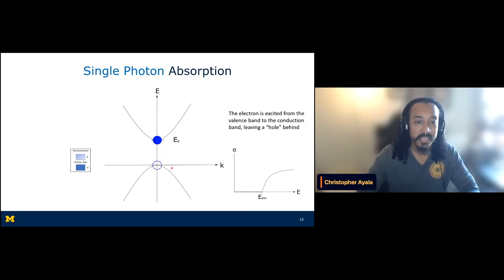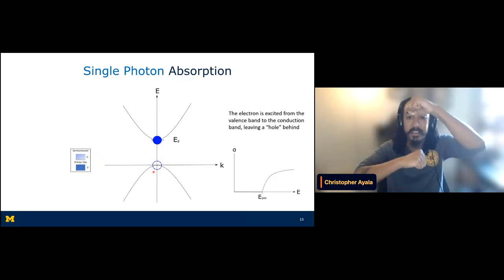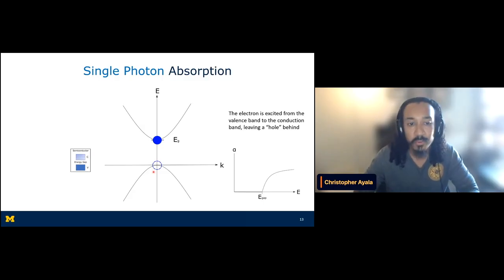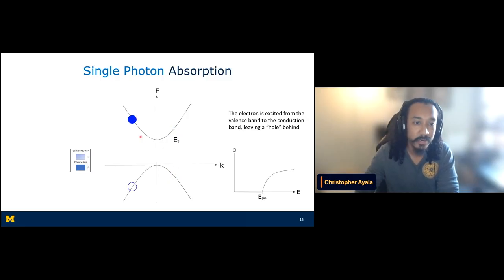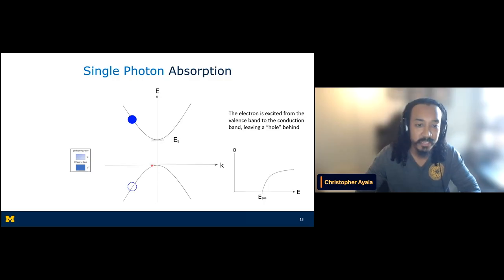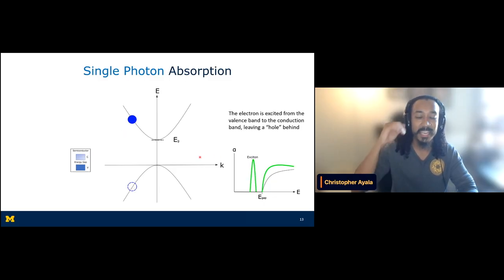And when an electron is excited from the valence into the conduction band, it leaves behind a hole. Note that this hole can form anywhere between the valence and the conduction band, here, for example, as well as out here. It's just most energetically favorable for the direct gap between the valence and the conduction band. What's neat is that if you start taking into account the Coulomb interaction between the hole and the electron, we may see what's called an exciton, which is a bound electron-hole pair that forms near the band edge or band gap.